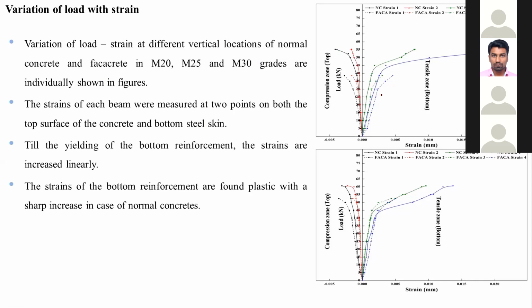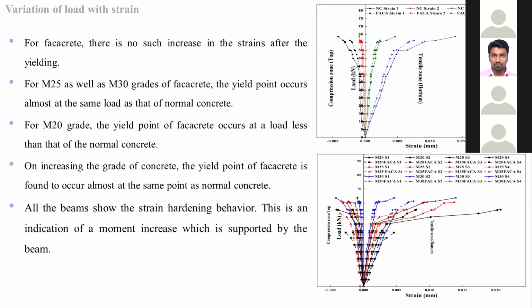We found that the strains of each beam were measured, and till the yielding of the bottom reinforcement, the strain increases linearly, up to the yielding point. The strain of the bottom reinforcement is found to be plastic, with a sharp increase in the case of normal concrete. And for M25 as well as M30 grades of facacrete, the yield point occurs almost at the same load as that of normal concrete.